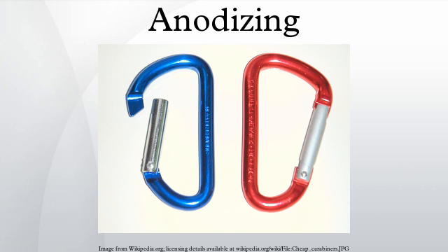The anodizing current varies with the area of aluminium being anodized, and typically ranges from 30 to 300 amperes/meter squared. Aluminium anodizing is usually performed in an acid solution which slowly dissolves the aluminium oxide. The acid action is balanced with the oxidation rate to form a coating with nanopores, 10-150 nm in diameter. These pores are what allow the electrolyte solution and current to reach the aluminium substrate and continue growing the coating to greater thickness beyond what is produced by autopassivation. However, these same pores will later permit air or water to reach the substrate and initiate corrosion if not sealed. They are often filled with colored dyes and/or corrosion inhibitors before sealing.